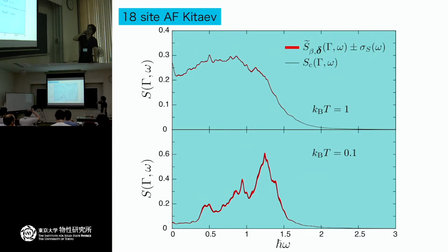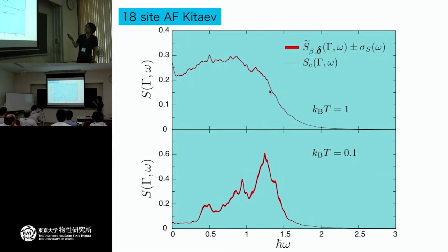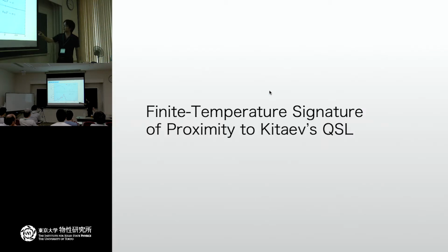Actually, let me introduce some benchmark results for the 18-site antiferromagnetic Kitaev-Heisenberg model. Here, it's more or less invisible, but the solid line is the exact diagonalization result with a finite width of 0.01. And the red band, or red area, represents the width of 1 sigma of the standard deviation. So in this sense, our algorithm more or less exactly reproduces the exact result for the canonical ensemble, reproducing even the really detailed finite size structure.